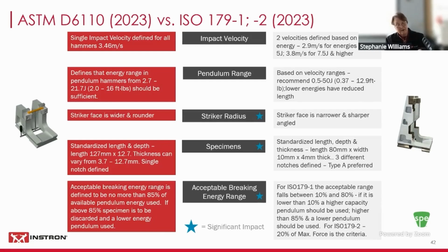Because it's wider, it engages further onto the area behind the notch. So the amount of material being impacted is going to be greater compared with ISO 179, where it is a much narrower, slimmer profile and has a tighter radius. So we have a smaller engagement area behind the notch. As I noted, the specimen lengths and depths are defined in the standards, as well as the notch. And then the acceptable energy range.